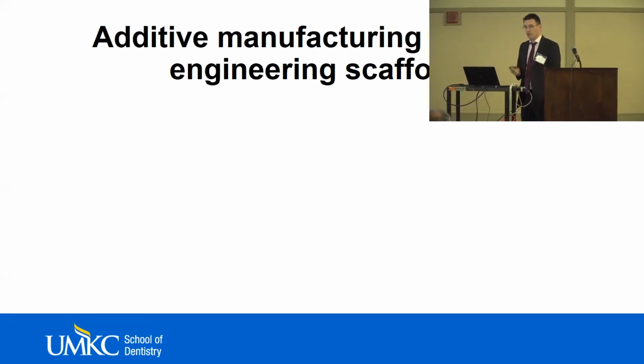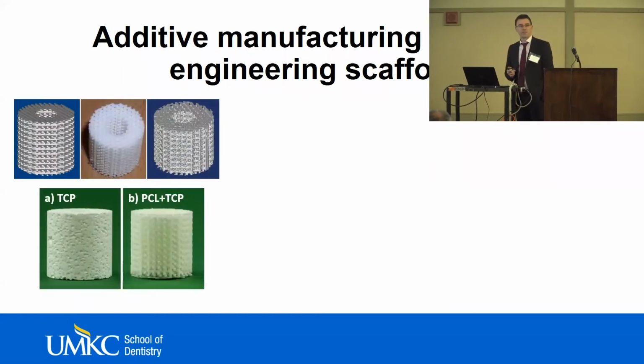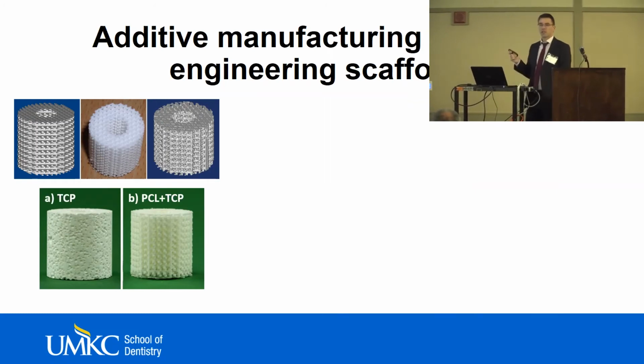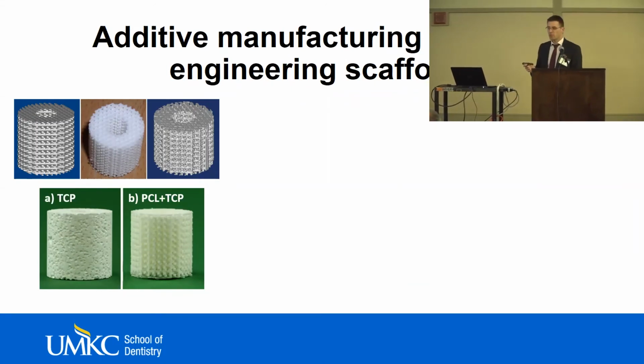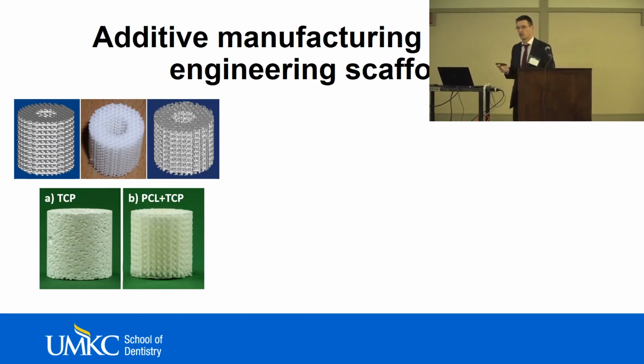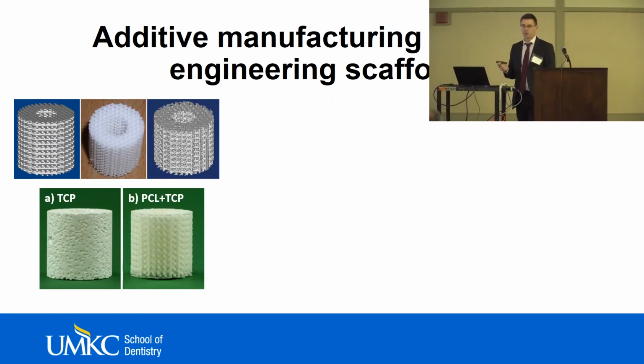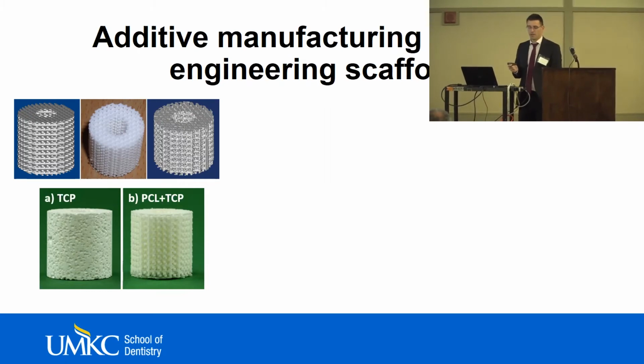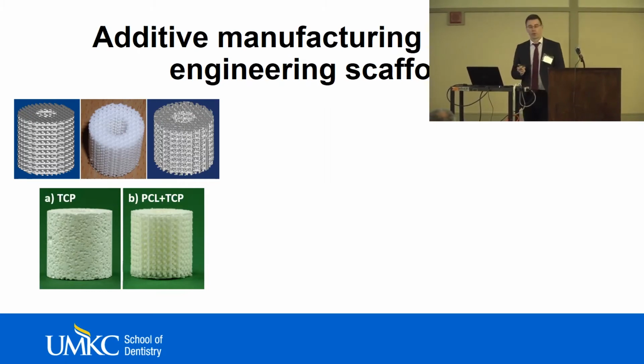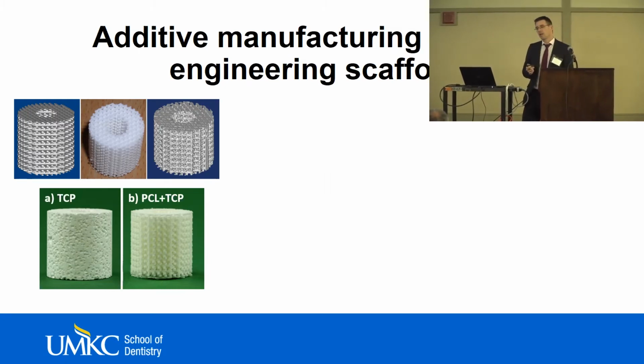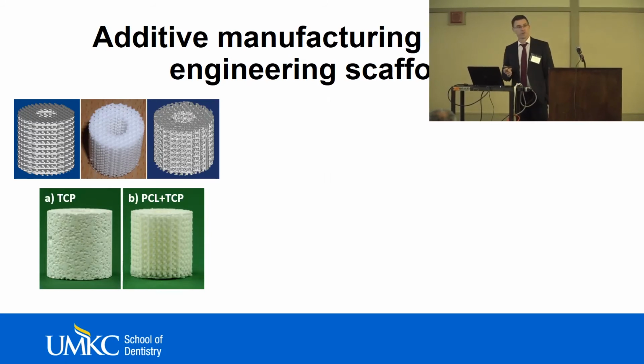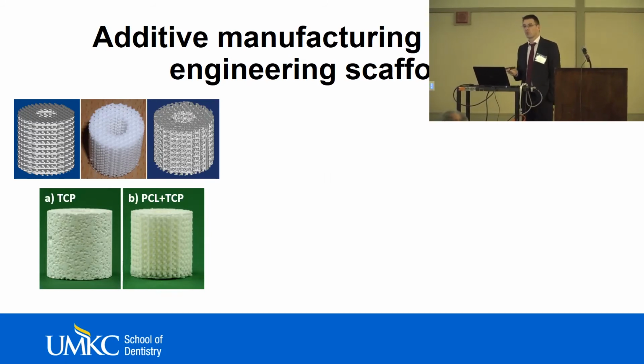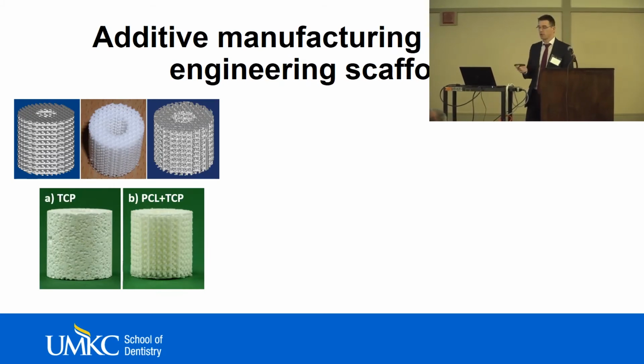I used what I had available in some of my previous research, and I used selective laser sintering, where a laser is used to heat and fuse powder particles in a powder bed together to form a three-dimensional structure. In this case, we used a polycaprolactone polymer, and we added 10% tricalcium phosphate to that material to enhance bone ingrowth into the scaffolds. We wanted to compare these novel scaffolds to the gold standard in bone tissue engineering, which is a pure tricalcium phosphate scaffold, to overcome some issues with this material. For instance, its brittleness, and that you have no control over the porosity, or size, or interconnectivity, and so on.